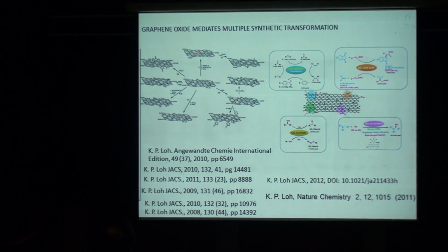Now, graphene oxide is just like graphene, except that it has a lot of oxygen functional groups attached to it. These oxygen functional groups can be of different types. It can be a carboxylic acid, COOH, which makes it acidic. Or it can be an epoxy group as well as a hydroxy group, OH, you see. Now, a COOH group makes this material an acid. This material has acidic property because it can undergo protonation and deprotonation. The hydrogen can be deprotonated or protonated. Once it's deprotonated, you get a carboxylate, COO minus, with a counter charge of sodium plus.